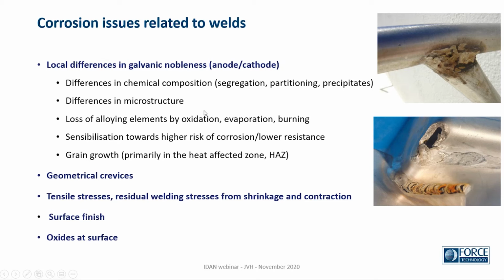We could have differences in the microstructure, and often that would be related to differences in the composition from solidification in the melts, segregation, formation of precipitates, which would be more or less noble compared to the base structure. We could lose alloying elements. Some of those that should give us corrosion resistance could be lost during welding, oxidized away, evaporated, or burned away. So we need to compensate for that.